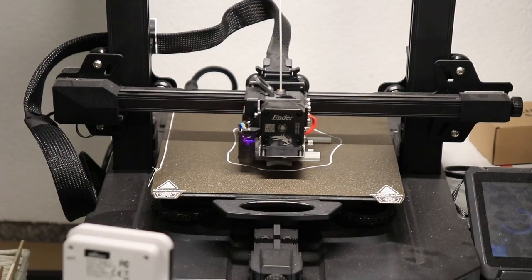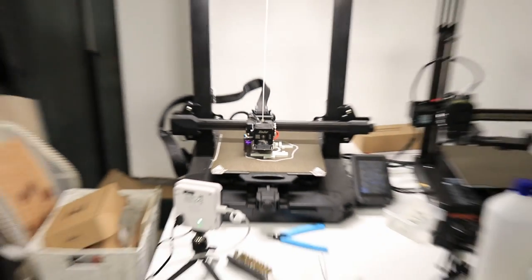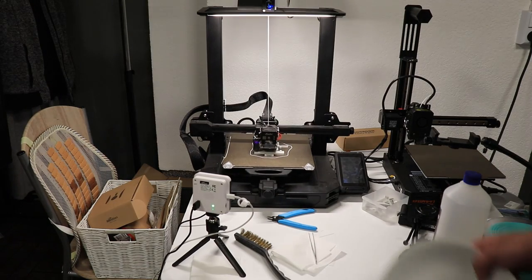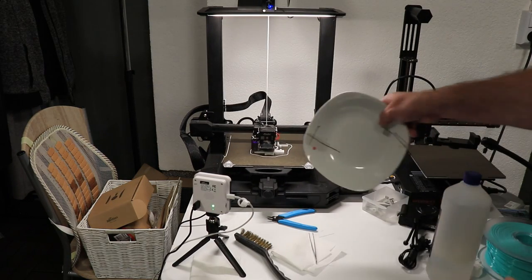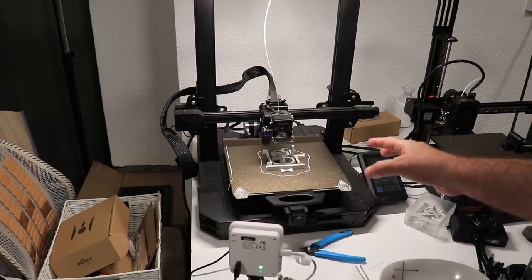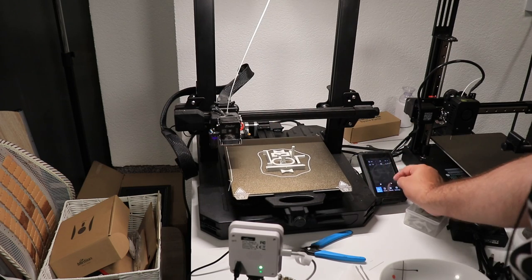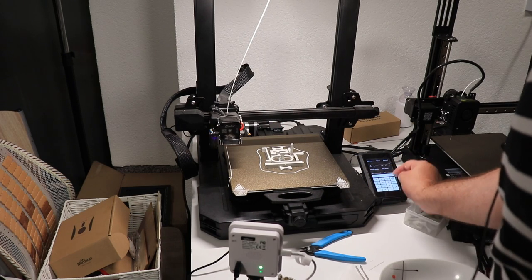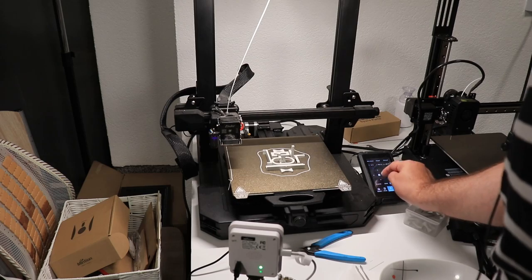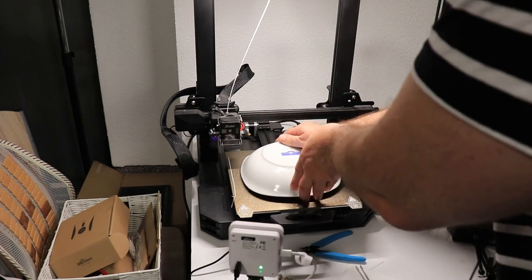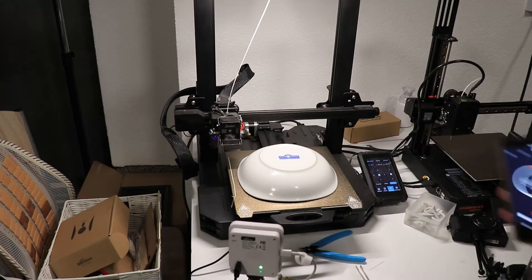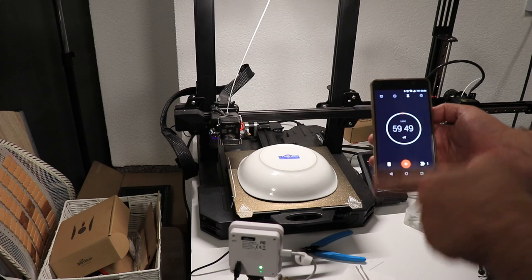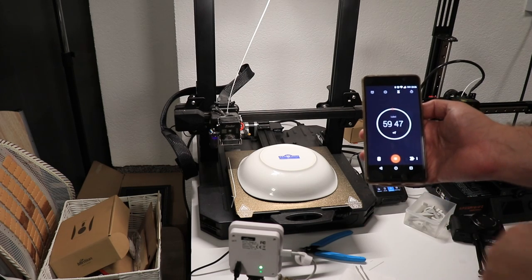This is the second group of the objects and I have to be here when it will be finished in approximately one hour to heat up the bed and to cover it. Printing is finished a few seconds ago and now first I will set the temperature of the bed to 100 degrees Celsius. And I set the timer. After one hour I will turn off the bed and leave it to slowly cool down. And now after one hour I can turn the bed heating off.